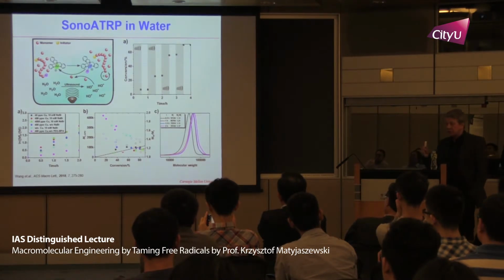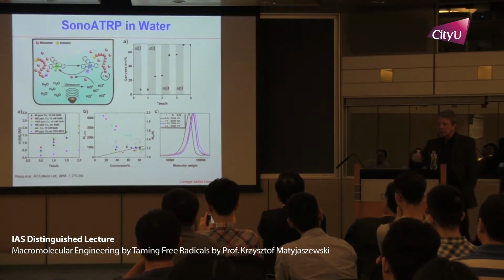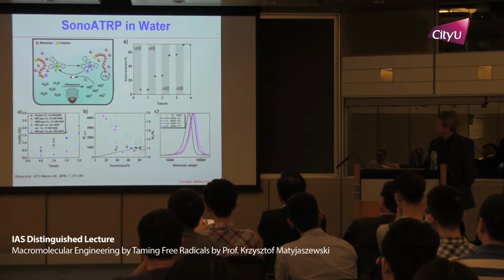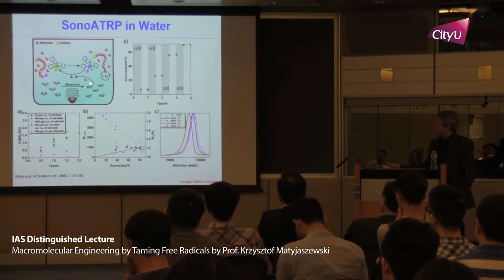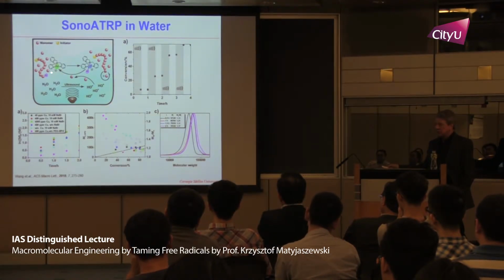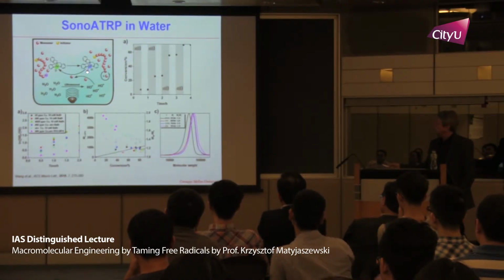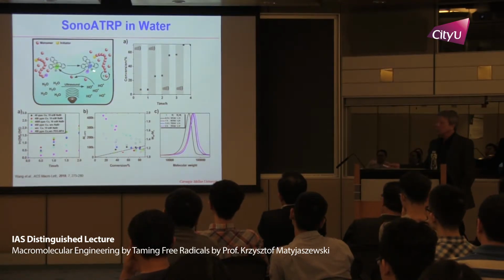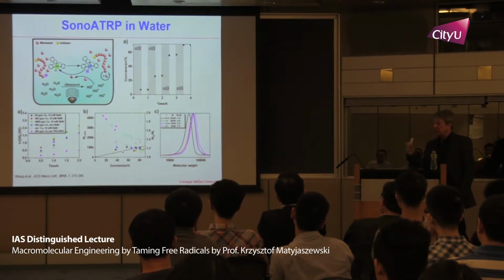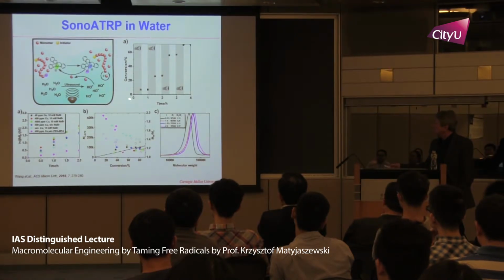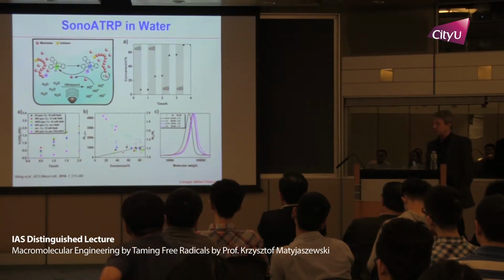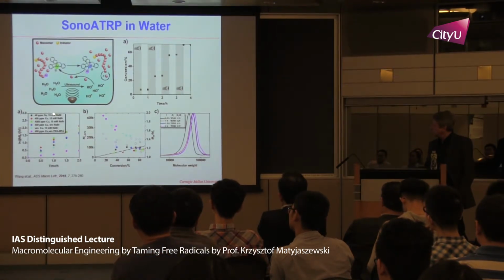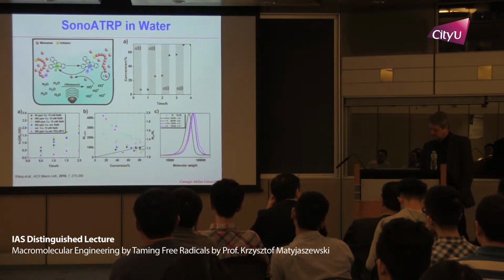So what happens in water, you use the sonication bath, just normal ultrasound. Water is split into hydroxy radicals. Hydroxy radicals initiate polymerization, forms carbon-based radicals. They take this bromine atom from copper 2, reduce it to copper 1, and polymerization goes like before. So you don't need any piezoelectric materials. It's enough in water to have the ultrasound on-off, on-off, on-off, and still good control of molar masses related to low dispersity, especially if you add a salt to this system.